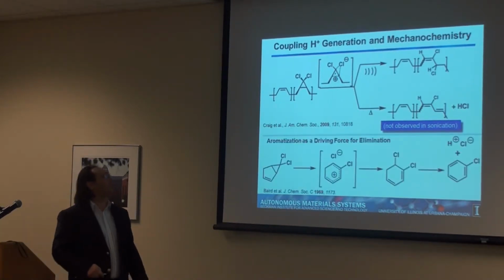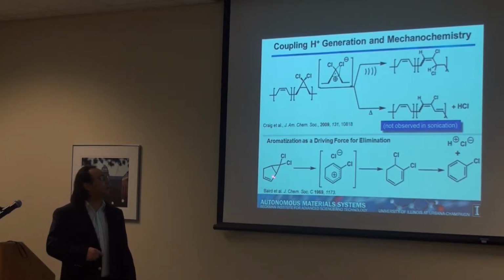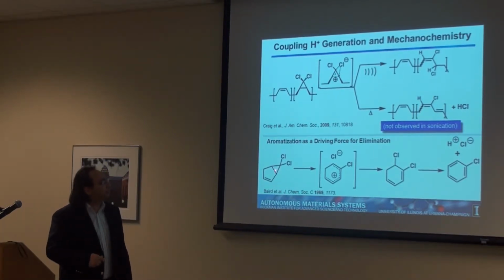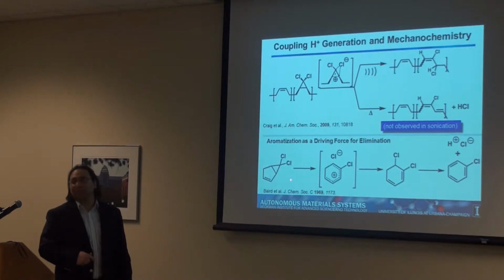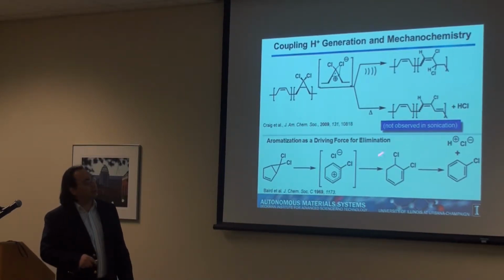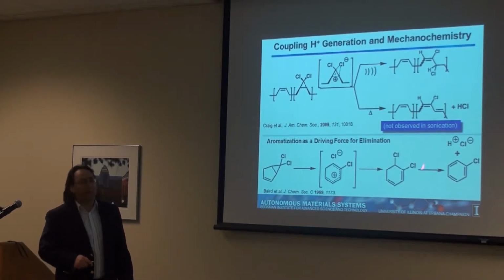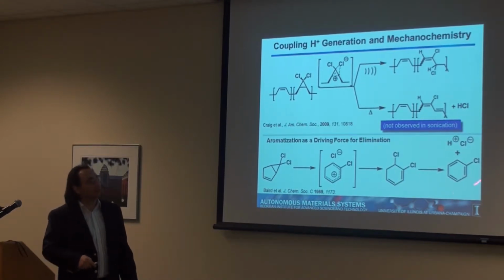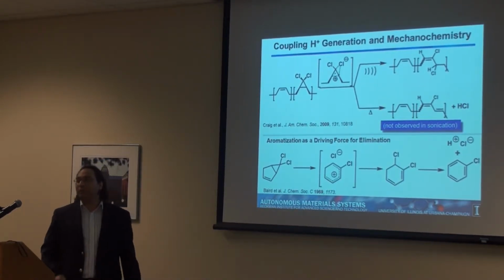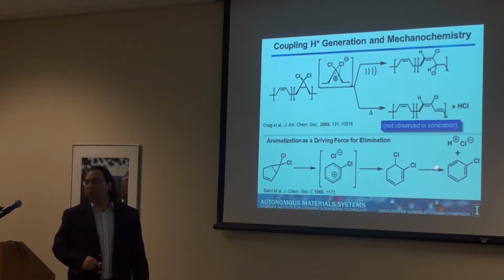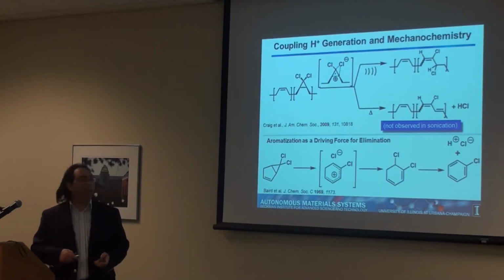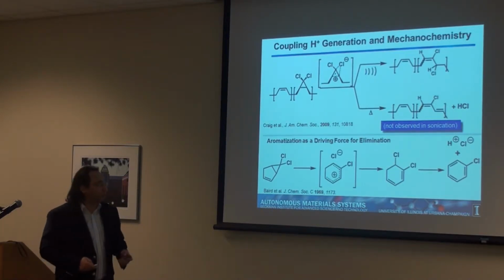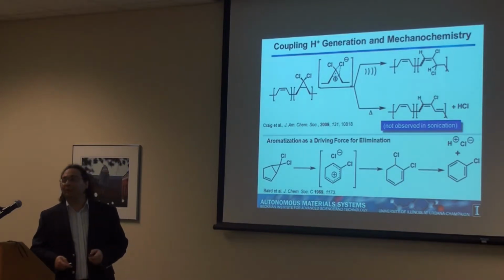Again, looking at the literature, it was shown a long time ago that if you have this dichlorocyclopropane embedded in a different cyclic system with a double bond, and you produce this molecule by the same rearrangement reaction, then this molecule will undergo spontaneous release of acid at room temperature to produce this aromatic system, this benzene ring, which is much, much more stable than this one. So you have a driving force for the release of acid after the rearrangement. So we said, great, let's prepare a system like this.